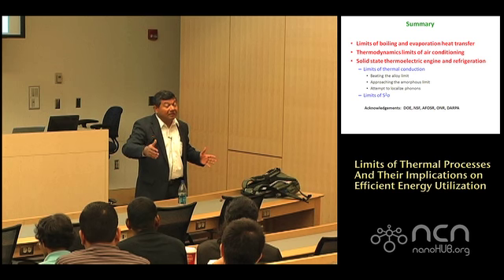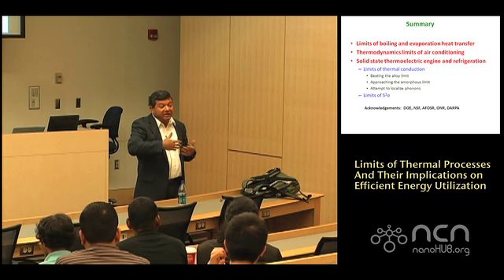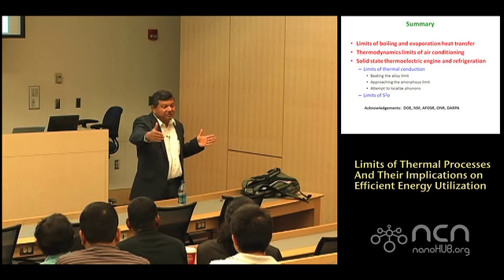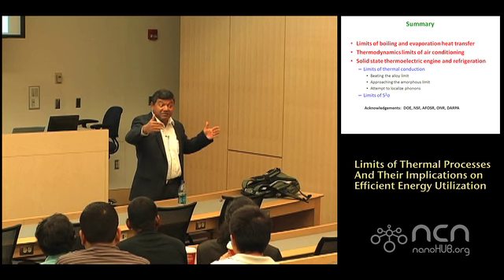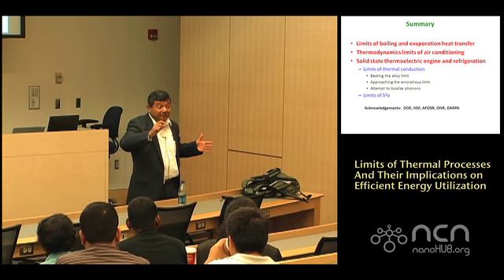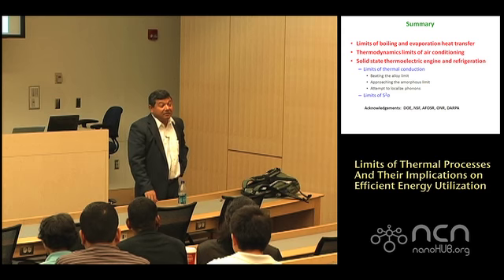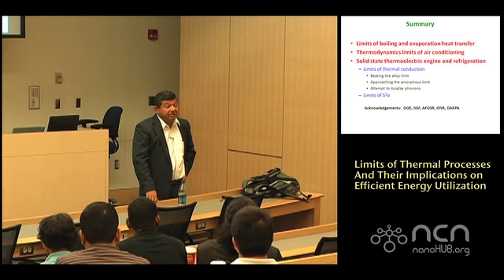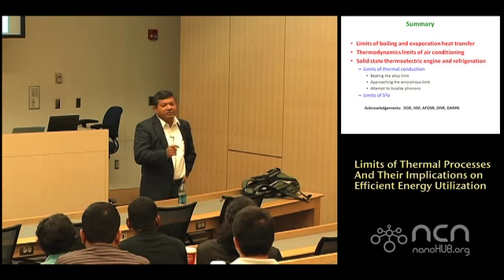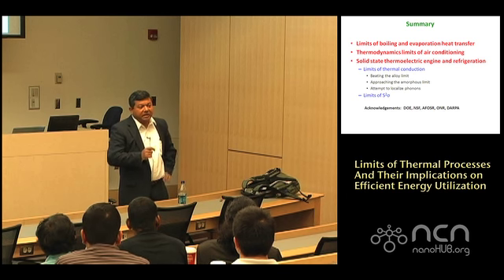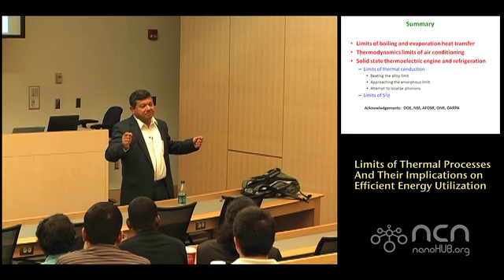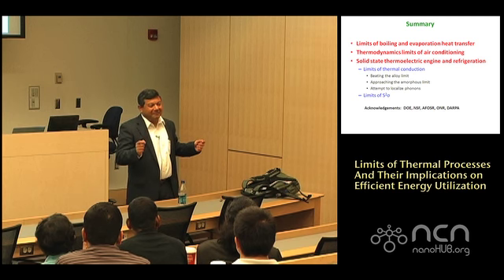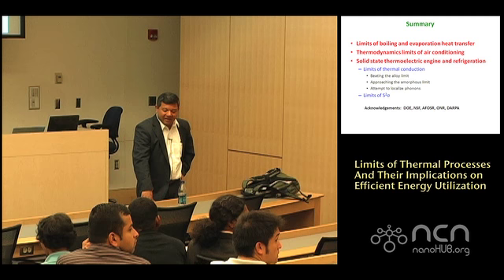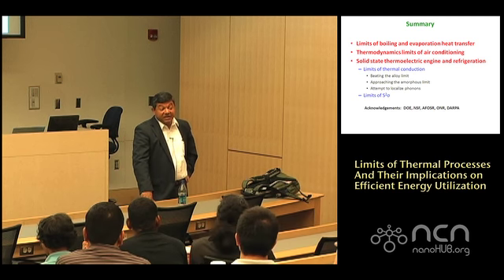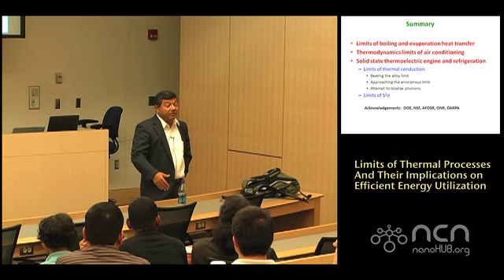So no one has been able to localize all the modes. And that's what we're trying out here, because if you make random roughness, as I said, the spectrum has to be broad enough and match the spectrum of the phonons. Then you get resonant coupling. That has not been done. I don't think anyone has actually seen it, because it's very hard to approach this through molecular dynamics, since I don't think you'll capture the length scales. It has to be a wave mechanics problem. Absolutely. But you have a chance of doing it if you get away from MD.